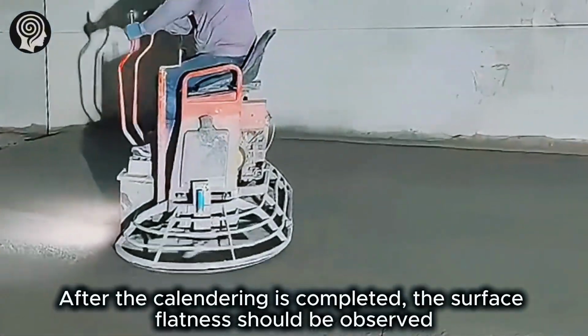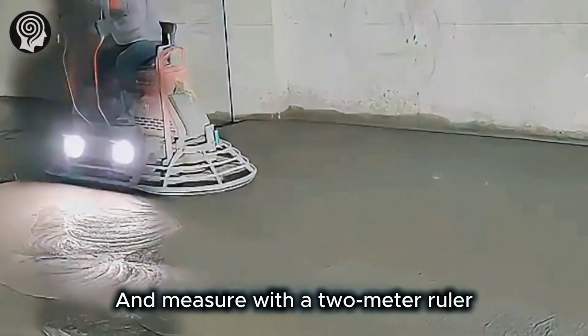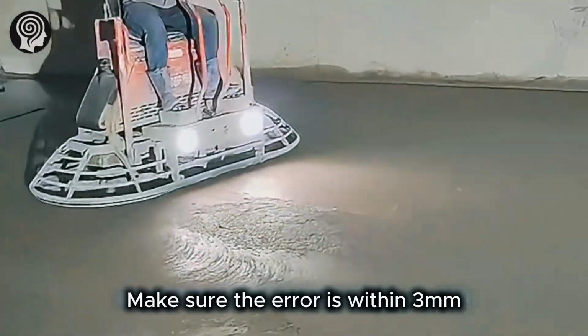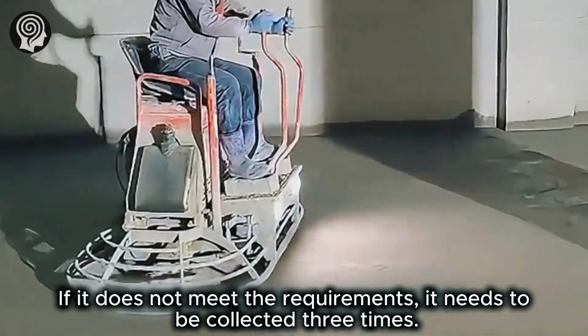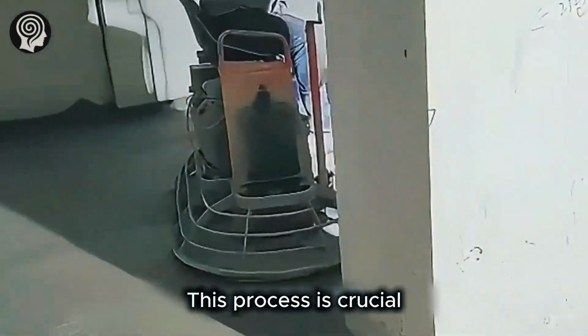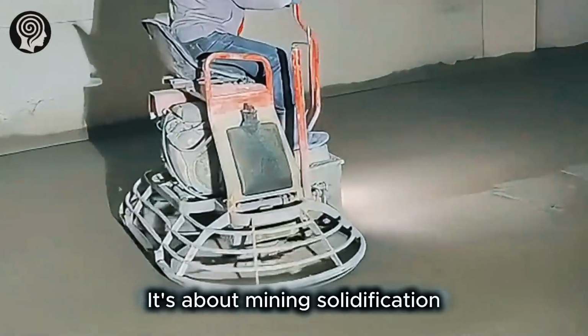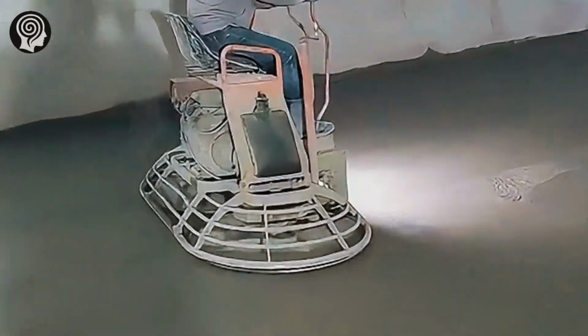After the troweling is completed, the surface flatness should be measured with a 2-meter ruler. Make sure the error is within 3 millimeters. If it does not meet the requirements, adjust it to meet the design requirements. This process is crucial. It determines whether the solidified ground can achieve the super mirror effect.